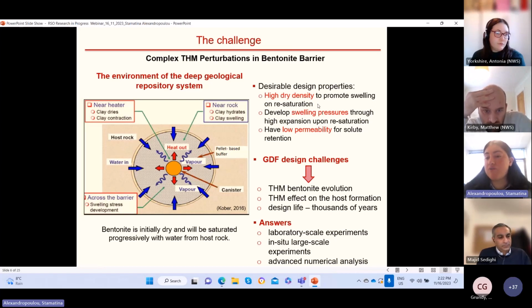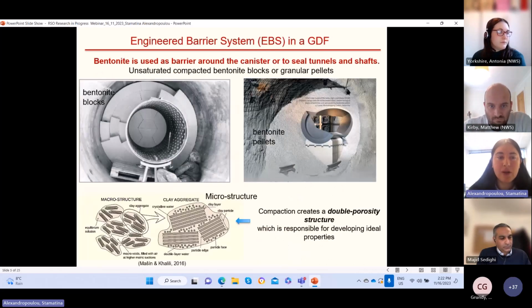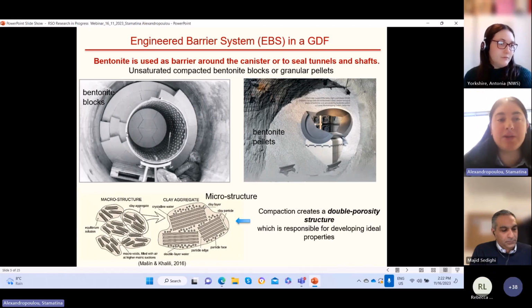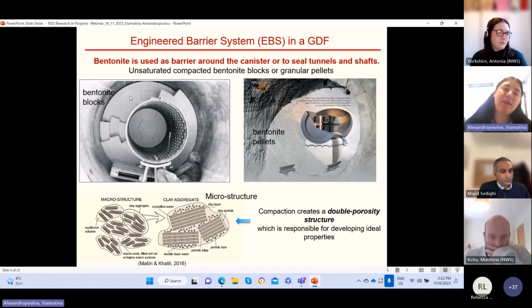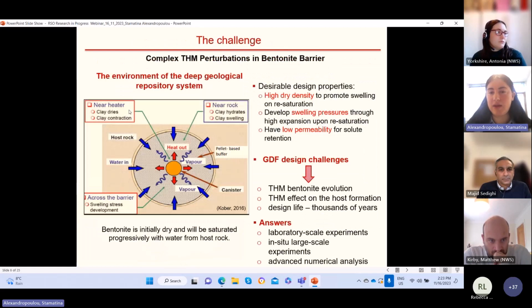So first, to have high dry density to promote swelling and saturation, and particularly if we go back again and we see on this image on the left-hand side, we can see that there are many voids, so the sealing is not full in the interface between the bentonite blocks and the host rock formation. So upon contact with water, the bentonite material will expand, and with this expansion, swelling pressures will be developed. Just to mention here that these swelling pressures should not be higher than the strength of the host rock formation, otherwise they will crack the rock.